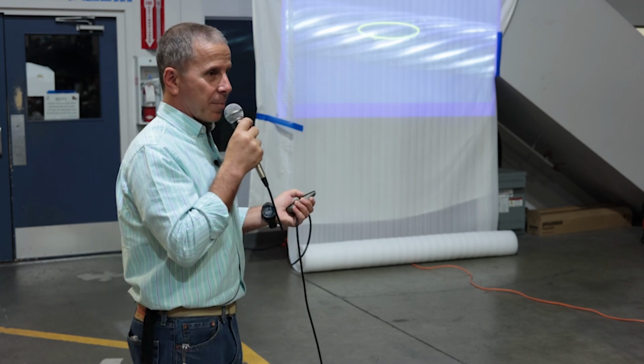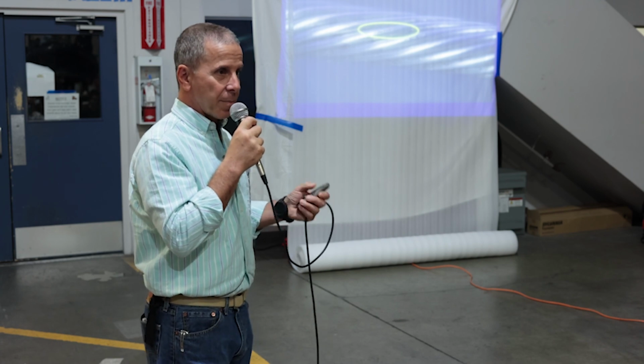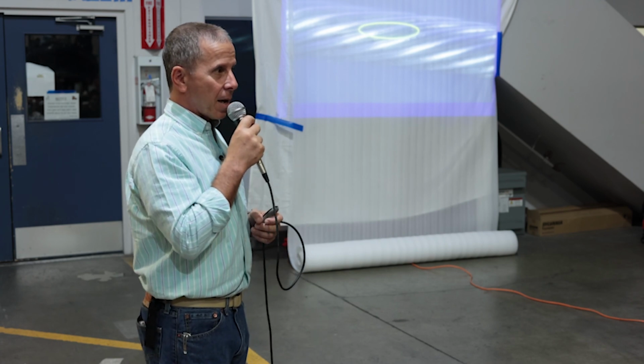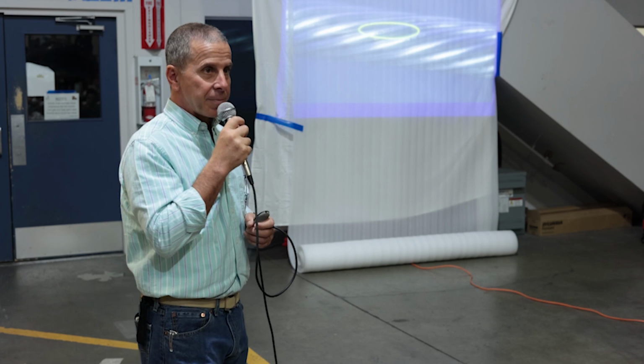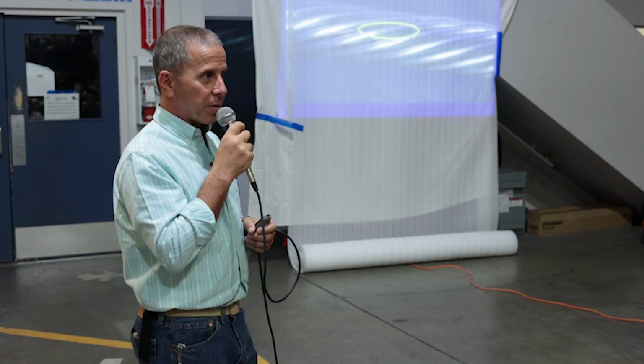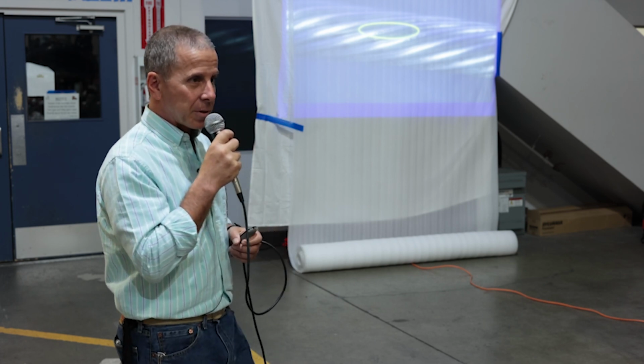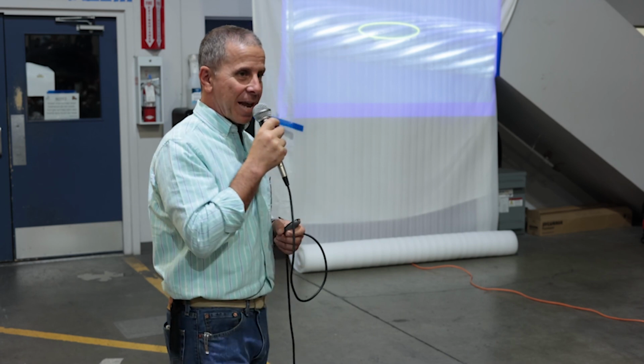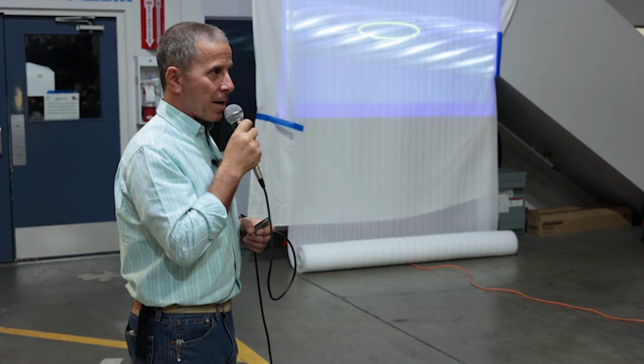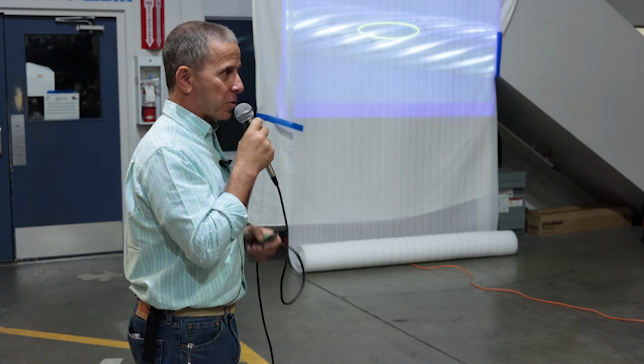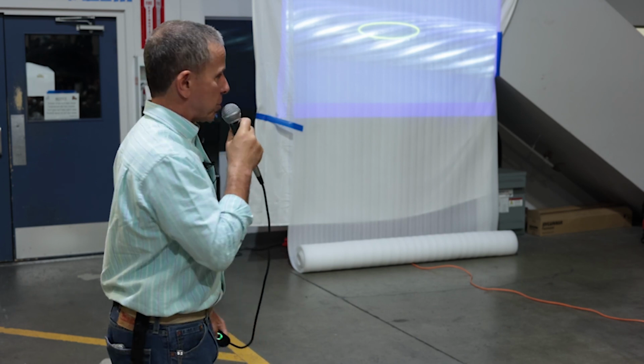So this is actually a piece of stainless wire that was covered with a PVC, not a coating, but a PVC tube that kept it wet all the time. Dirt got into there. There was probably some what looked like green mold or bacteria as well that was growing, and that kept the environment damp and oxygen depleted, and it eventually led to pitting corrosion on that wire.